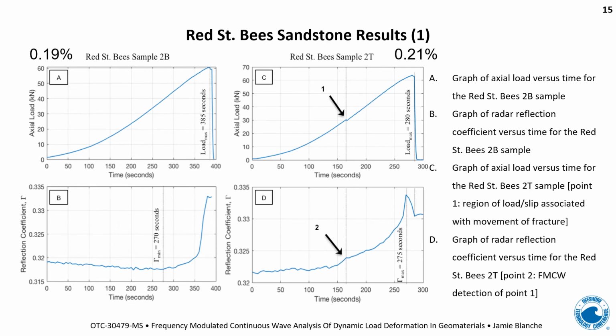For the Red St sample, it's a very similar story to the Darney sandstone. We load to failure and we see a general decrease in the reflection coefficient to a trough point, which occurs well in advance of that fail. Now for the second Red St sandstone, we see a slightly different result. This is interpreted to be because there was a fracture or some slippage within the layering that has been observed within that sample. This is denoted by point 1, where we see this very brief relaxation in the load profile.